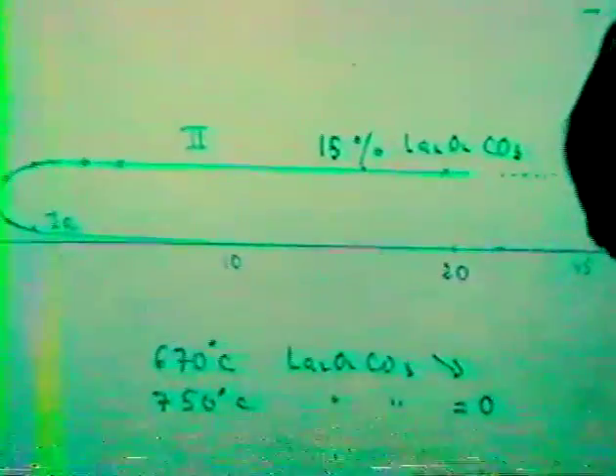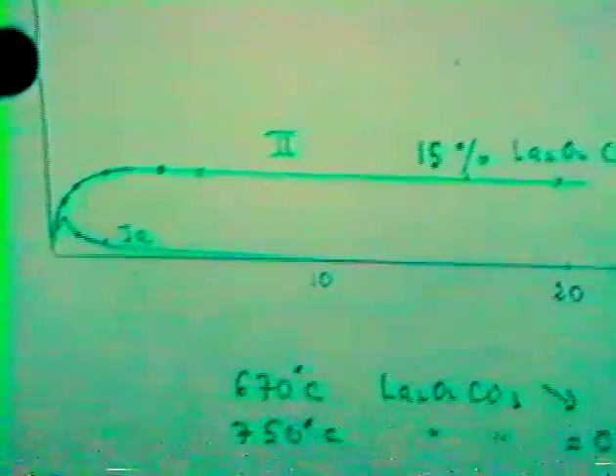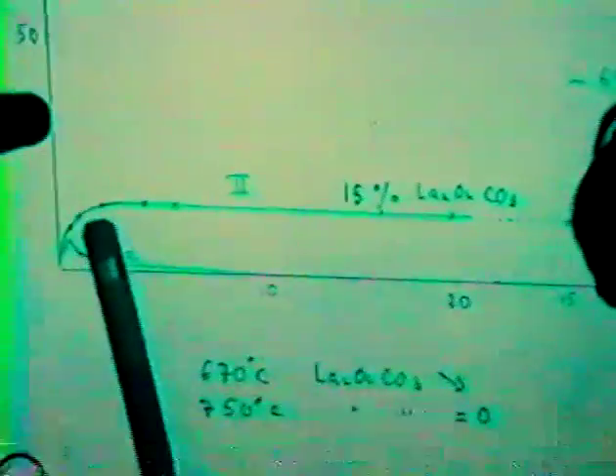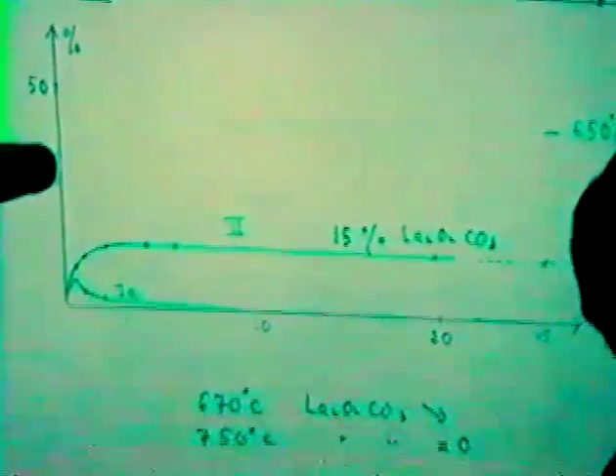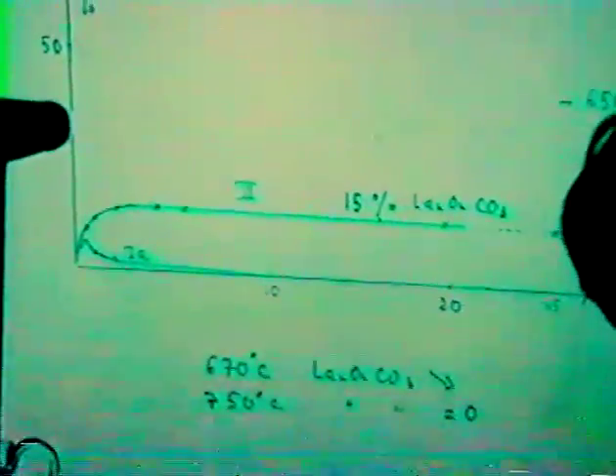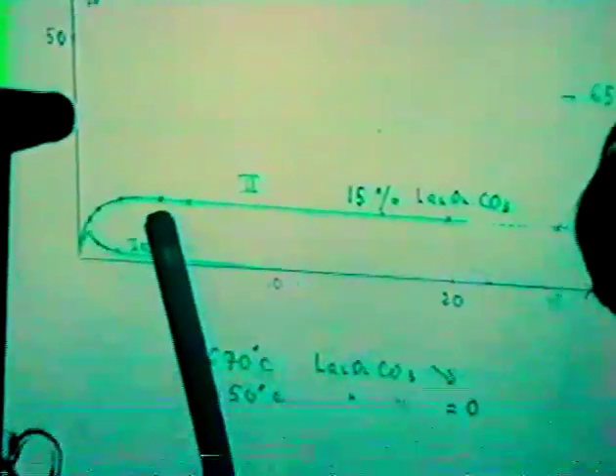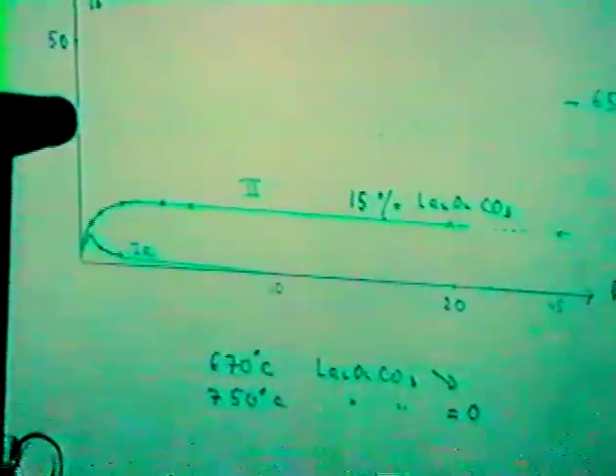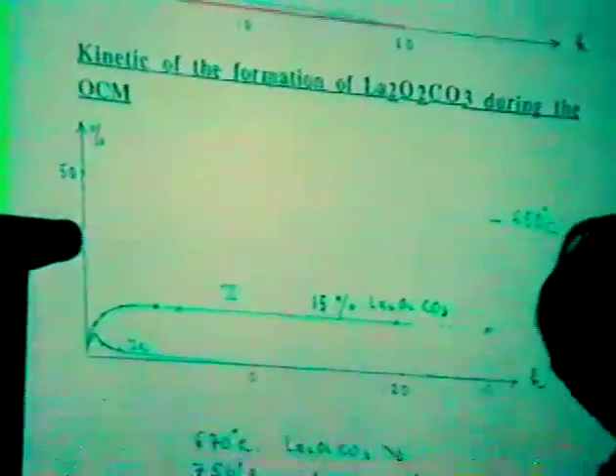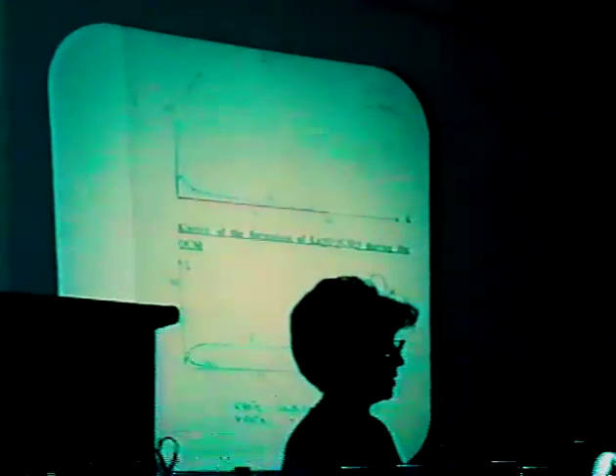Now, when the oxidative coupling of methane is performed at the same temperature, that is at 660 degrees, in contrast to the preceding results, you observe beyond 2 hours a constant amount of the oxycarbonate. We have performed this experiment during 45 hours, maintained it, and the amount is still constant. We observed that 15% of the initial oxide is converted to the oxycarbonate.